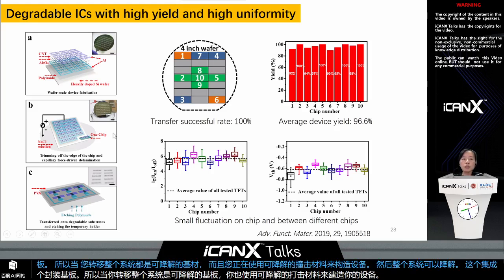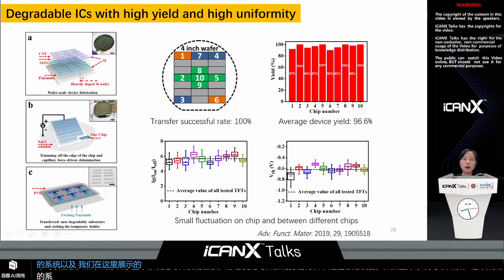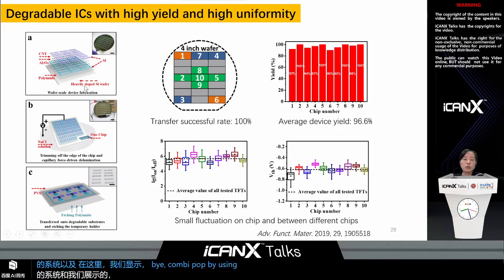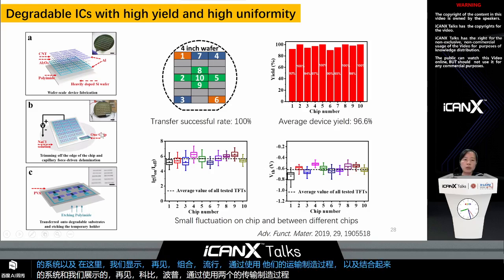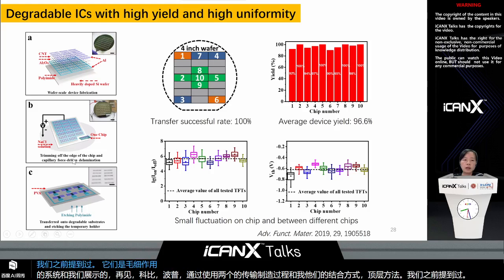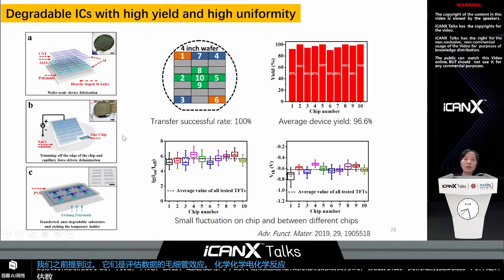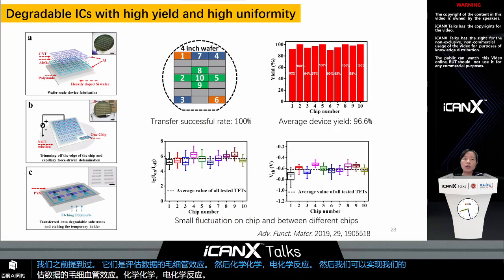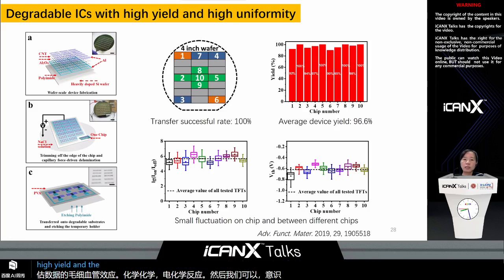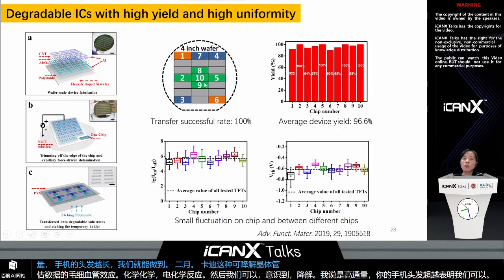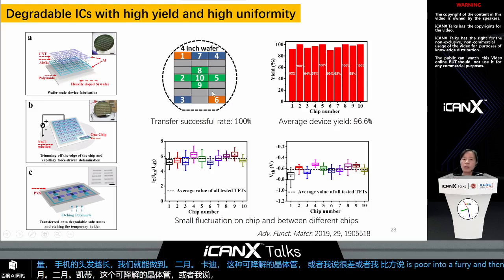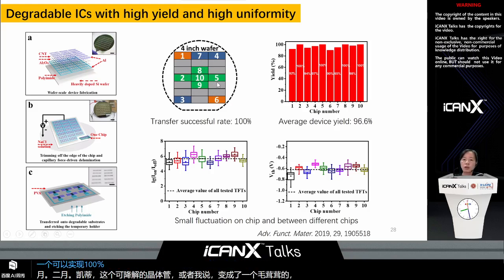And here we show that by using the transfer fabrication process, combined with the delamination method we mentioned before, the capillary effect assisted electrochemical reaction, we can realize our degradable ICs with high yield and high uniformity. Here we show that we can fabricate these degradable transistors or ICs on a 4-inch wafer. And first, it can realize a 100% transfer rate.